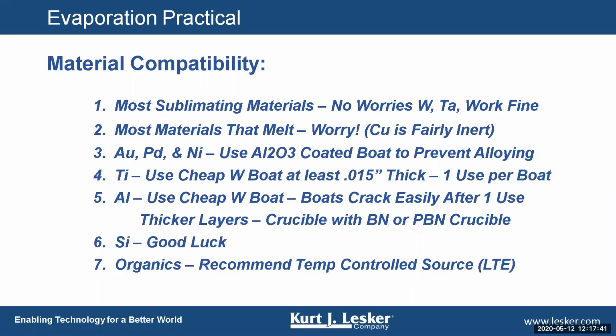And I realize titanium is usually a thin layer. For aluminum, again, I use cheap tungsten boats. Aluminum makes any refractory metal boat crack very easily. It makes coils that evaporate it crack very easily. And generally with crucibles, we recommend boron nitride or pyrolytic boron nitride crucibles.